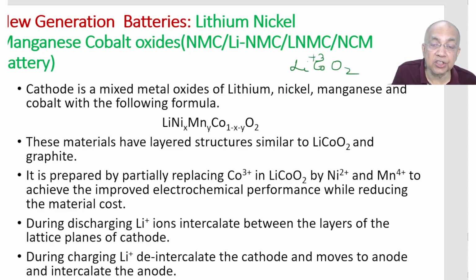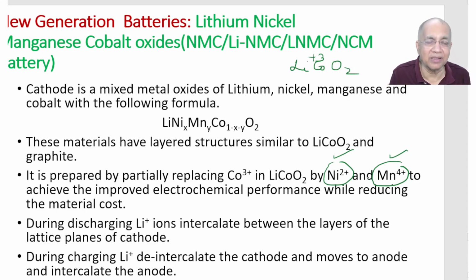So this is the original structure of the cathode material. Now this is cobalt +3 in the crystal; at several places cobalt 3+ is replaced by nickel 2+, and in other places manganese 4+. Suppose for the replacement of 2 cobalt 3+, the charge is +6, and one of them is Ni2+, the other one is Mn4+, so the total charge is 6+. So there is no charge imbalance. The stoichiometry is restored. But in place of cobalt 3+, at some places you will find nickel 2+ and also Mn4+.